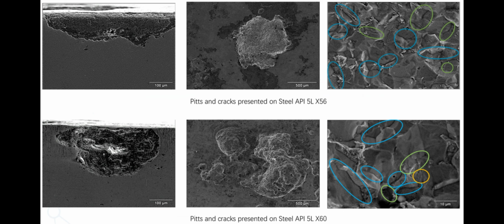The pits found in the samples lacked the typical morphology of pits caused by electrochemical corrosion. SCC-induced pits showed greater dissolution inside them and did not have a spherical morphology. Subsequently, we evaluated the pits with scanning electron microscopy to confirm the occurrence of SCC-induced cracks. It was found that crack formation occurred in both steels with transgranular cracks. This transgranular cracking is characteristic of non-classical SCC, being more predominant in steel number 2, that is the X60 steel.